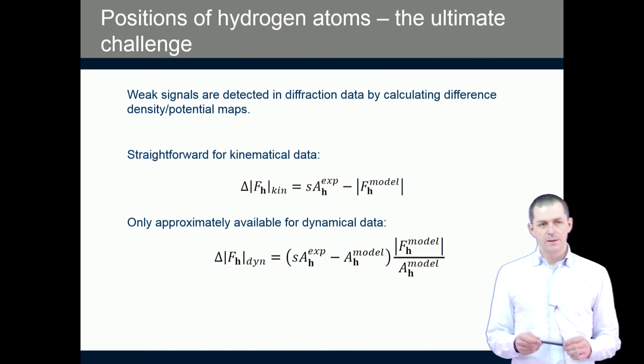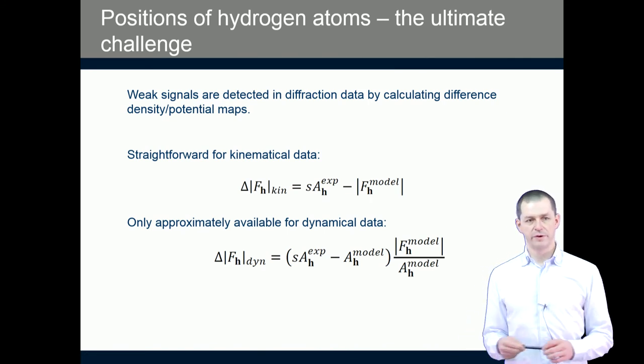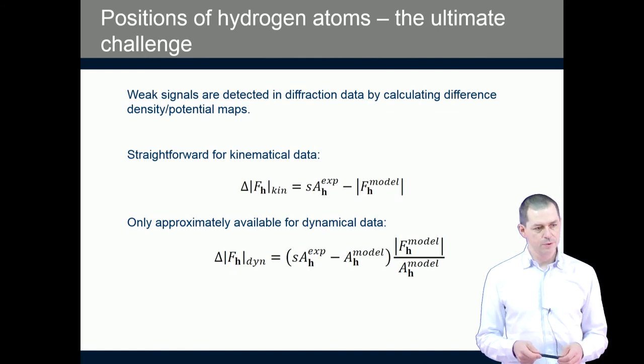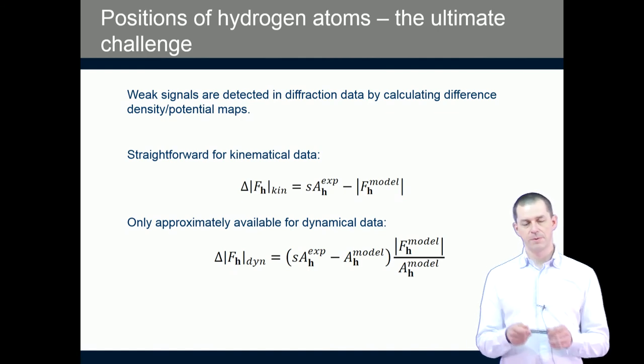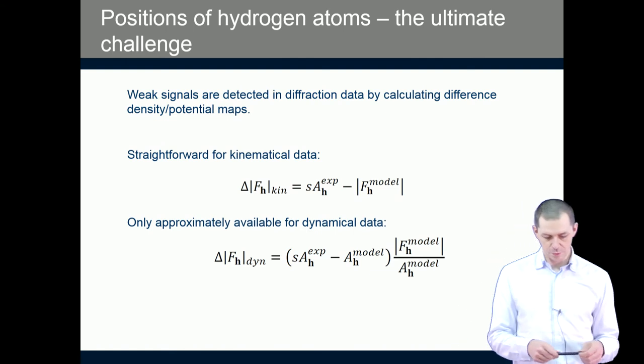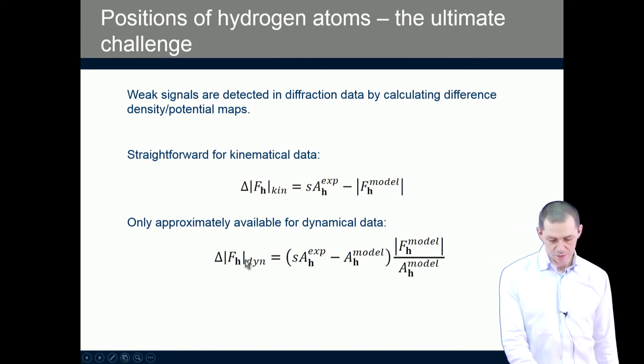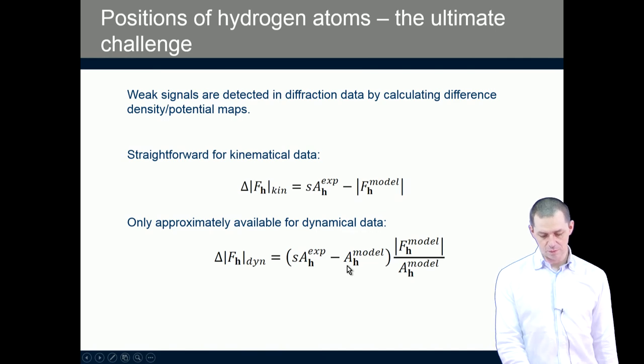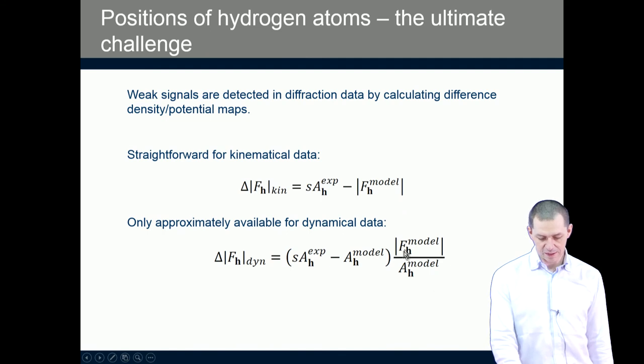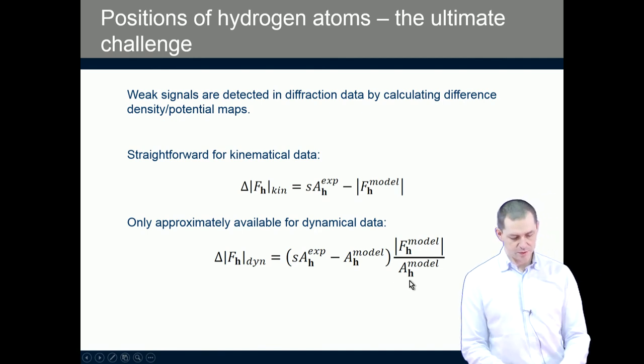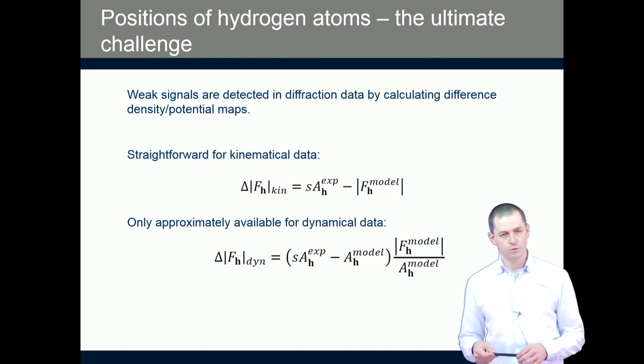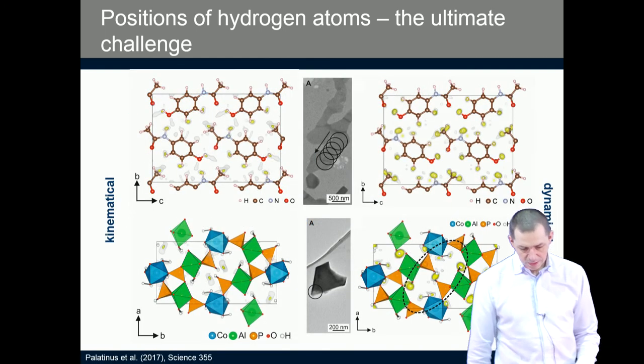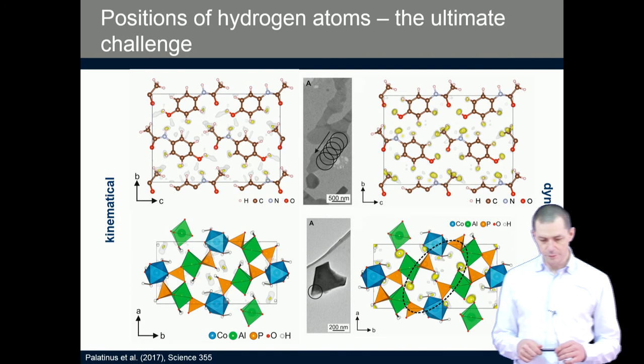In dynamical diffraction, we do not have direct access to experimental structure factor amplitudes, because the intensities are not a simple function of structure factor amplitude. So we need to make an estimation of the difference by looking at the difference of the intensities, or square roots of intensities, and scaling it by the ratio between the structure factor amplitude of that reflection and its model intensity. So it's an approximation, but it turns out to work quite well. And this is the result of our efforts.